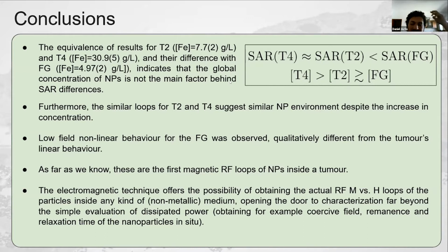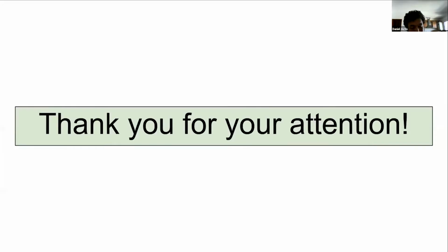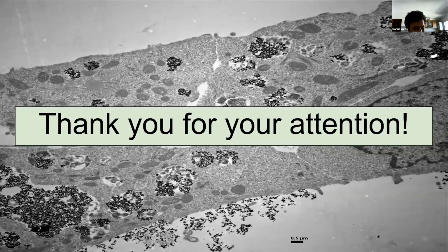From there, we can obtain not only the SAR, but also the coercive field, the remanence, and the relaxation time of the particles from having the complete magnetization versus field loop. And we obtain all this information in situ, in the same medium where they will be applied, in this case inside a melanoma tumor. So, that being all, I thank you very much for your attention, and I'll be now open to your questions.